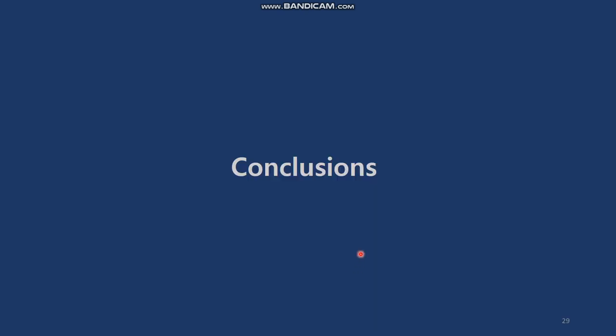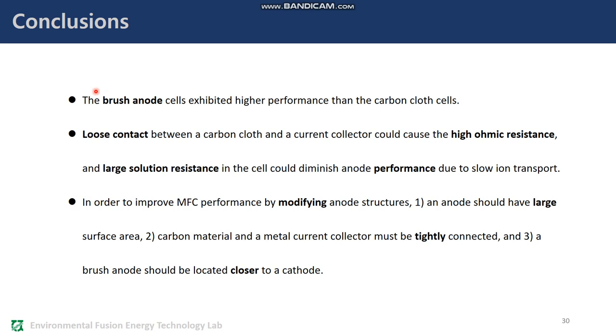Conclusions. The brush anode cells exhibited higher performance than the carbon cloth cells. Loose contact between a carbon cloth and a current collector could cause the high ohmic resistance. And large solution resistance in the cell could diminish anode performance due to slow ion transport.